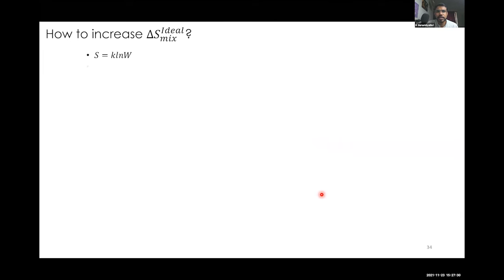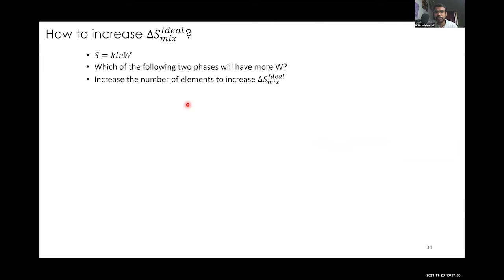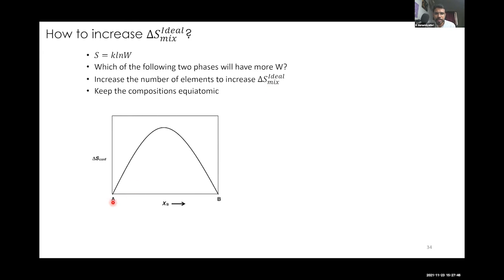So how to increase this delta S ideal mixing is by increasing the number of elements. Increase the number of elements to increase the delta S. So keep the compositions equiatomic. This is another piece of information. Now look at this graph. It says if you have a two element system and you calculate the configurational entropy for that system, which comes from a formula based on K natural log of W, you will have this kind of shape. At the middle, it is maximum, like the 500 heads, 500 tails case.